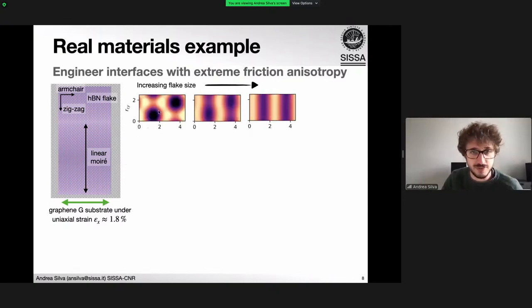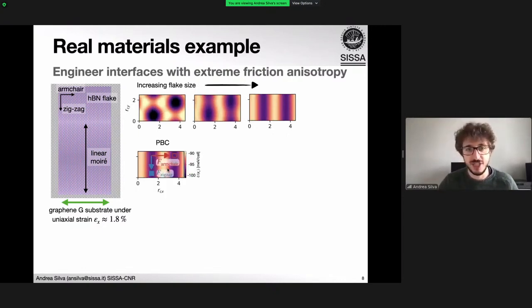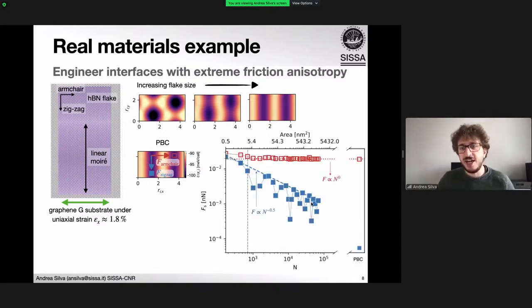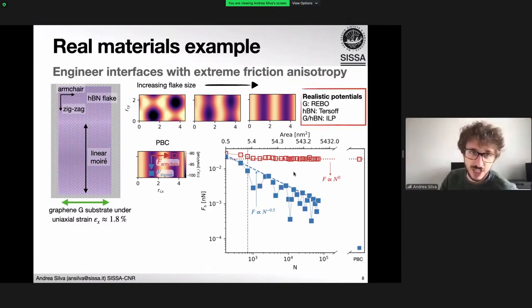So the system goes from the usual hexagonal moire pattern, and as the size grows, it develops this valley, up to the infinite limit system where you have perfect valleys in between them. And then we can probe the friction sliding perpendicular to this valley or parallel to them. And we find a scaling of the friction in the two directions, which is very much in agreement with what the theory expects. Of course, the situation here is more complicated because we use realistic potentials, not some approximated Gaussian.